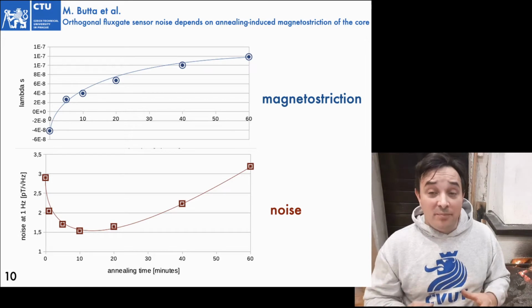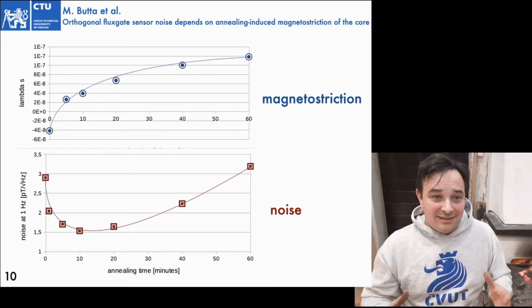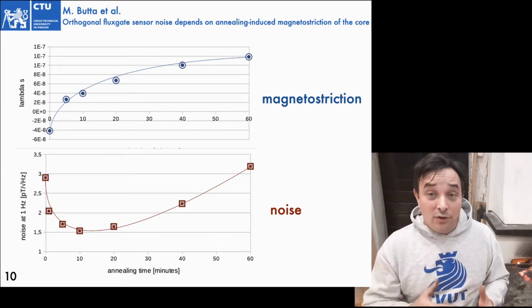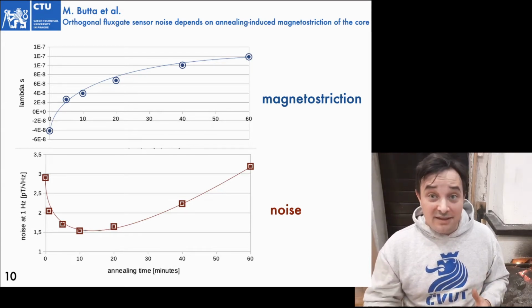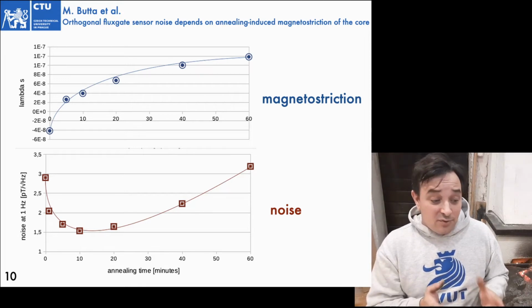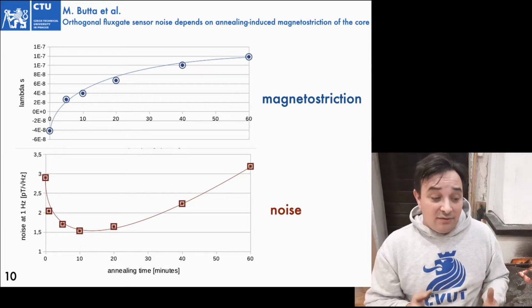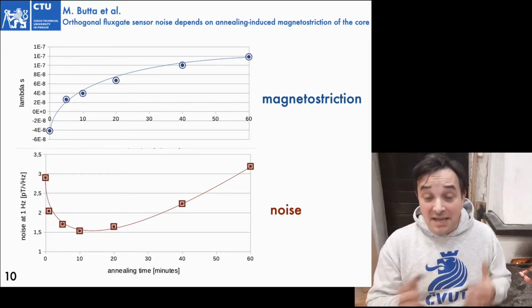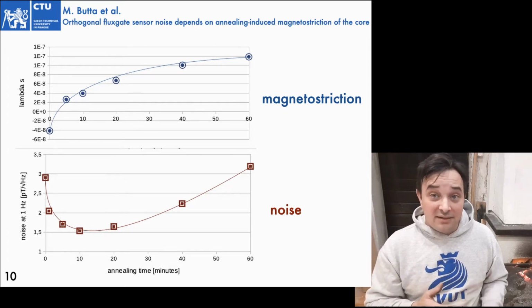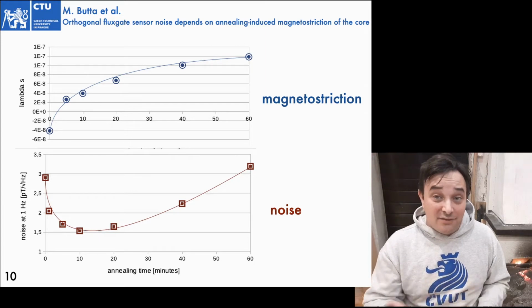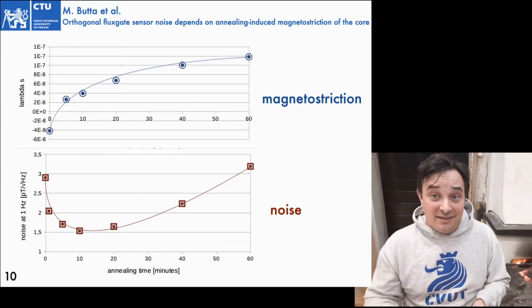And that is the problem, because for long time annealing, well, yes, the circumferential anisotropy increases, but not that fast. On the contrary, the magnetostriction still increases. So where do we find the lowest noise? We have a sweet point about 10 minutes because, as a matter of fact, at 10 minutes you still have the same magnetostriction that you have for a cast wire. It's just opposite sign. Instead of -4 is +4 10 to the -8. But the amplitude itself of the magnetostriction is the same.